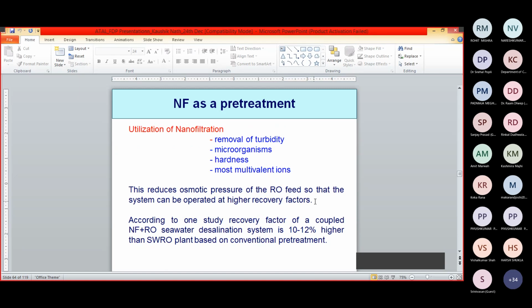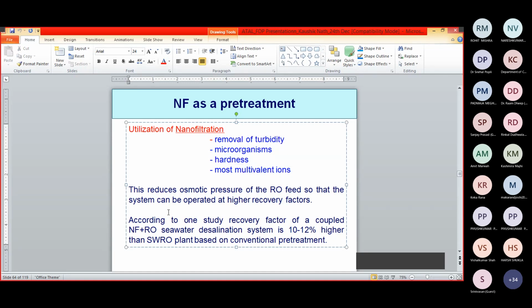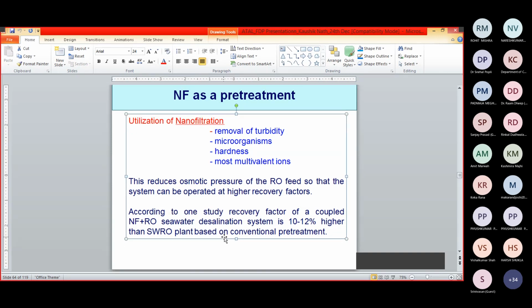So for NF as a pre-treatment, I will give one or two examples. Nanofiltration can be used in the pre-treatment stage for removal of turbidity, and it can be used for microorganisms to some extent. Hardness and most multivalent ions can be removed. This reduces the osmotic pressure of the RO feed so that the system can be operated at a higher recovery factor. According to one study, the recovery factor of a coupled system, that is a combination of RO and NF, for seawater desalination is 10 to 12% higher than SWRO. SWRO means spiral wound reverse osmosis. The spiral wound membrane is very widely used and popular, a spiral wound reverse osmosis plant based on conventional pre-treatment. So this can be used.